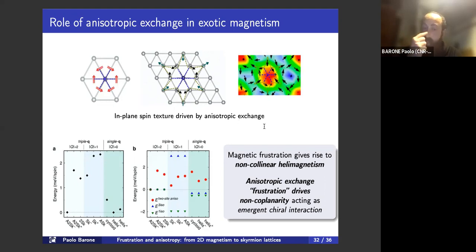The other interesting thing is that this is related to the fact that this frustrated anisotropy occurs on a triangular lattice. Basically, when we have this triple Q state, this anisotropic exchange frustration acts as an emergent chiral interaction. What does it mean? That we can compare the energies of chiral partners of the same structures, for instance, this anti-Skyrmion with opposite chiralities. And if we look at the energy contribution of the different terms, they of course have the same energy contribution coming from the isotropic interaction, but what makes them different is exactly this anisotropy, which removes the chiral degeneracy between these two states.